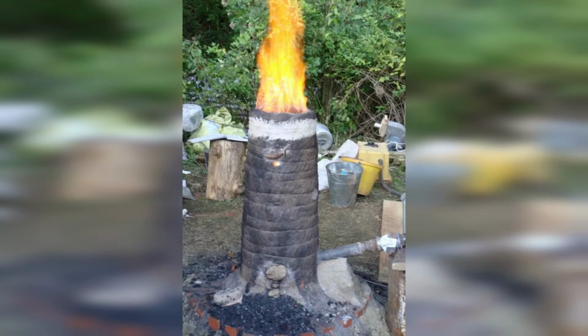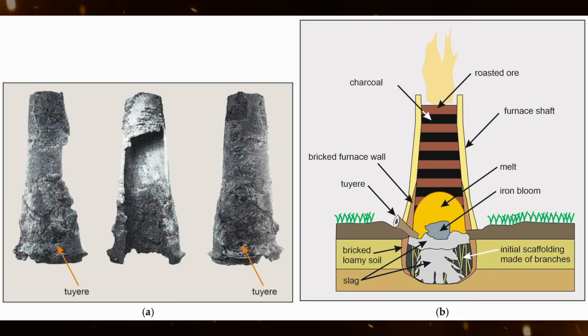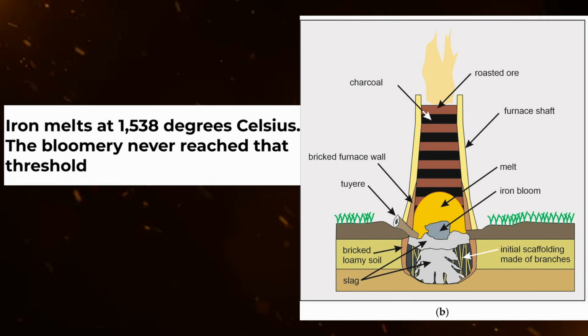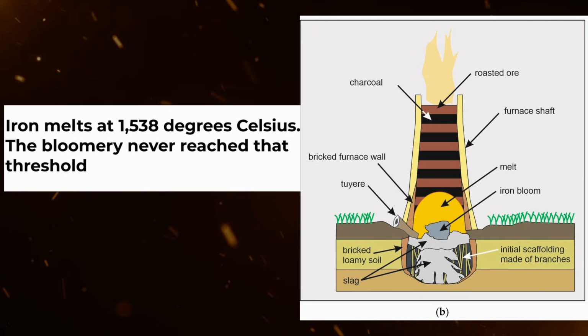The technology that created this superior iron was brutally simple. The bloomery furnace was a clay and stone chimney standing only as tall as a person. Inside, layers of charcoal and iron ore were stacked together, while bellows forced air through pipes at the base. The key was temperature control, or rather the deliberate lack of precise control. A bloomery operated at roughly 1200 degrees Celsius, hot enough to chemically reduce the ore, but crucially, not hot enough to melt the iron. Iron melts at 1538 degrees Celsius. The bloomery never reached that threshold.